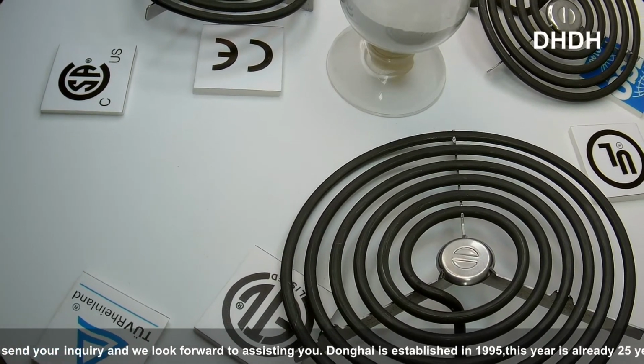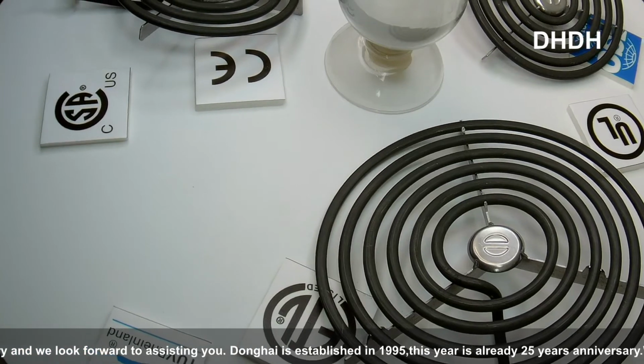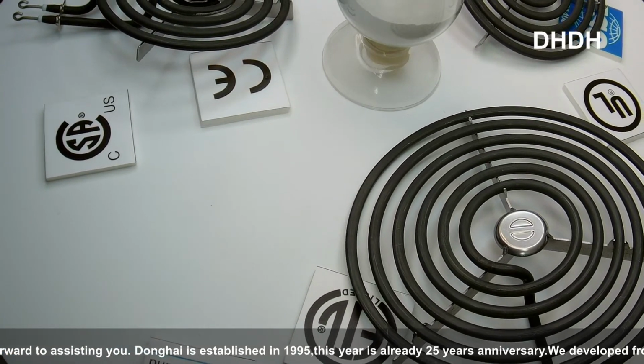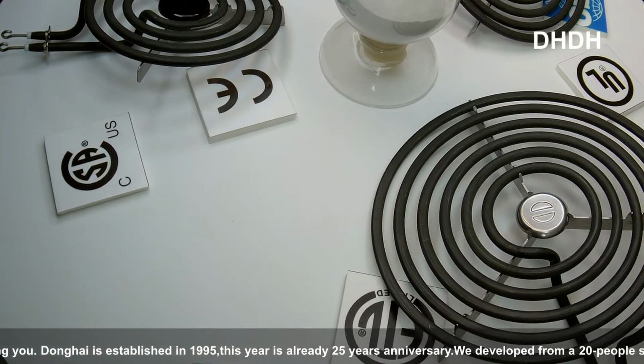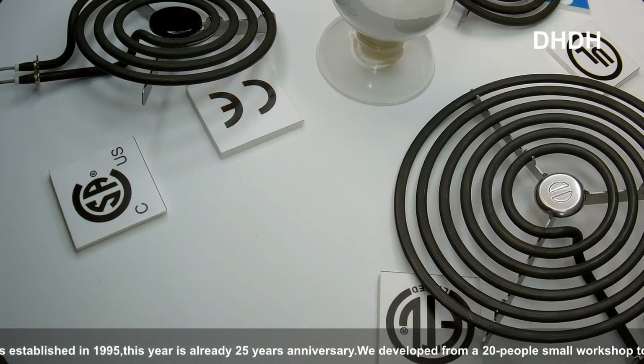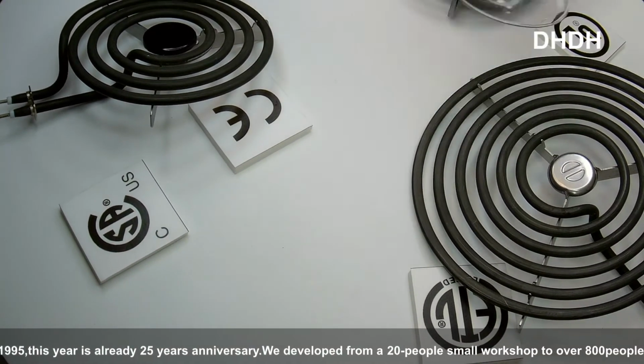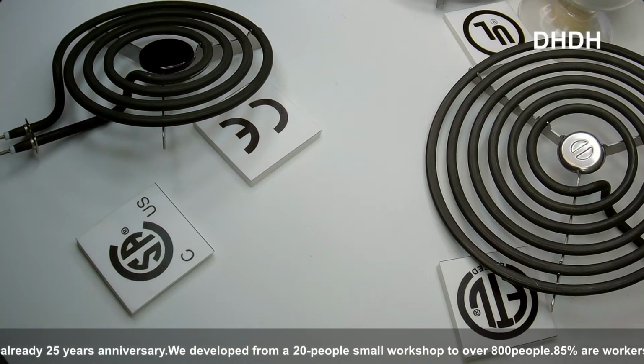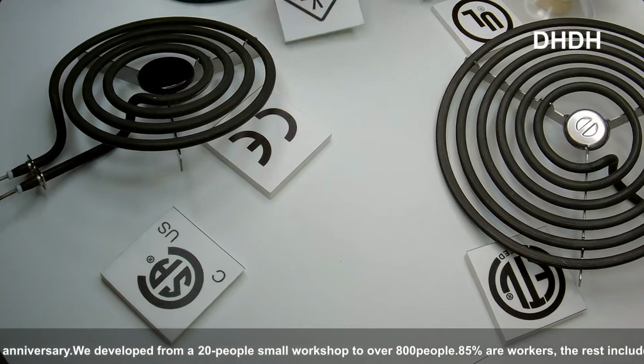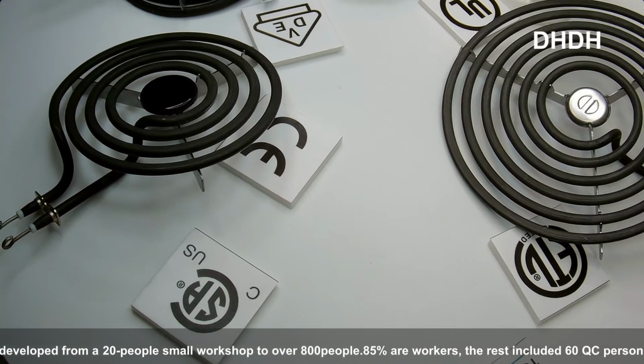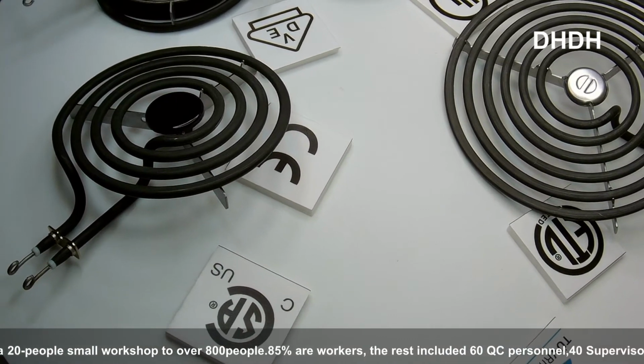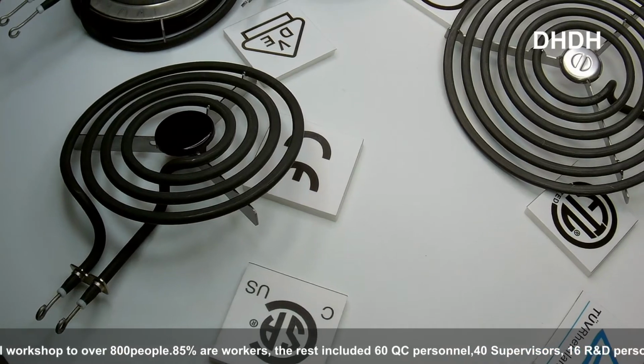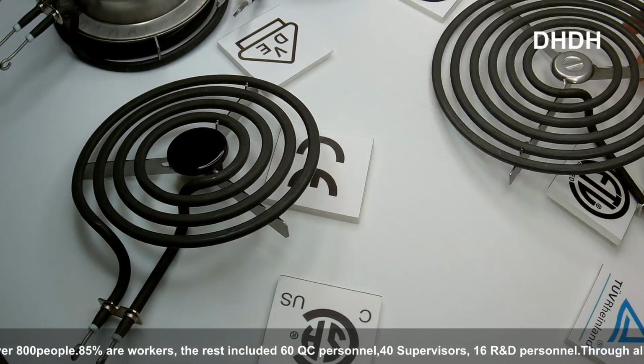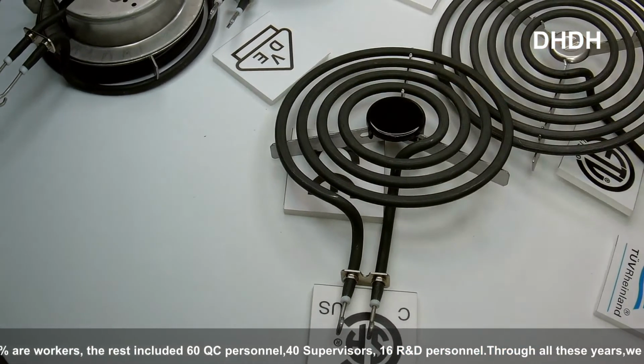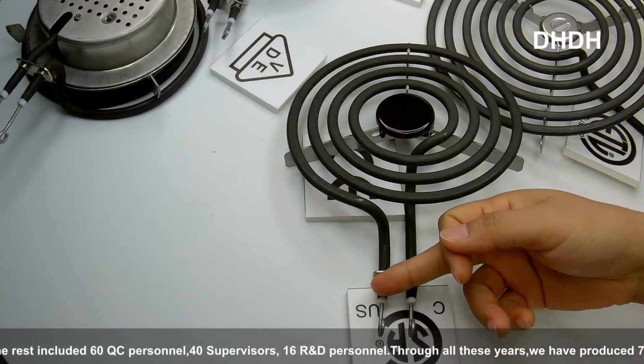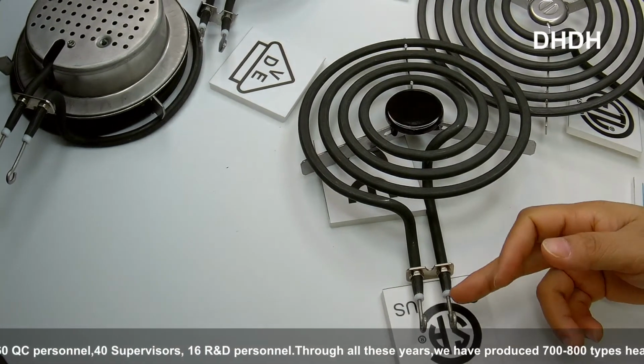So you may be interested in how we deal with the moisture-proof problem. With our experience and study of MGO for many years, we have our own way. Simply speaking, when the tube comes out of the annealing furnace and the temperature cools down to a certain degree, we coat some moisture-proof material on both nozzles. Yes, we apply the moisture-proofing on the nozzles, and then we tighten the plugs.